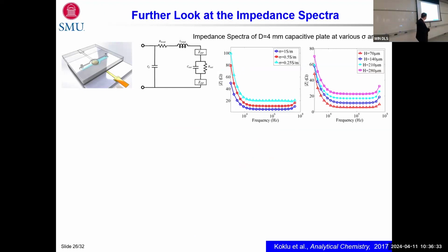All right. So we basically created, again, a capacitor plate design up there, which was basically a large electrode, 4 mm diameter with various heights. And we were also changing the conductivity of the fluid. The effects I'm showing you here are quite minimal because I'm using very large electrodes. All right. So as the electrode shrinks and the conductivity increases, these variations in impedance get very wild and spread through the entire frequency regime. So to use this in true microfluidics, we have to really eliminate it.